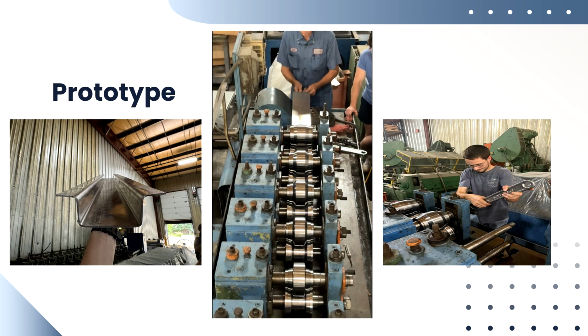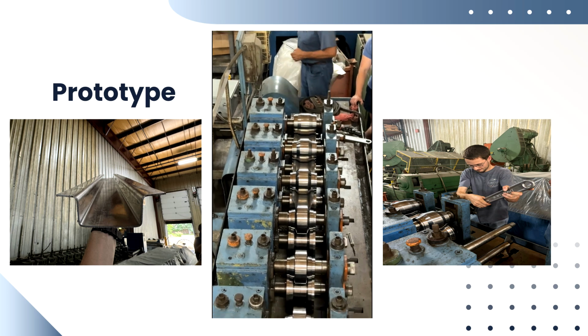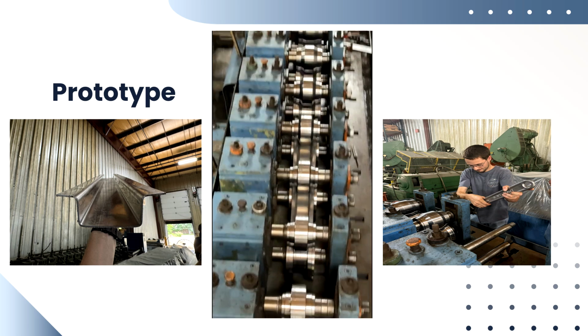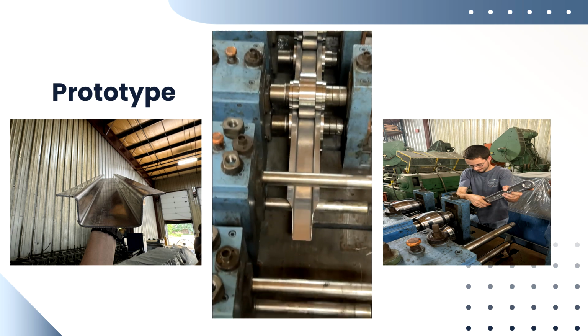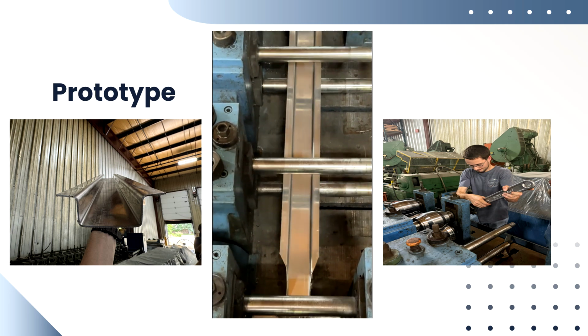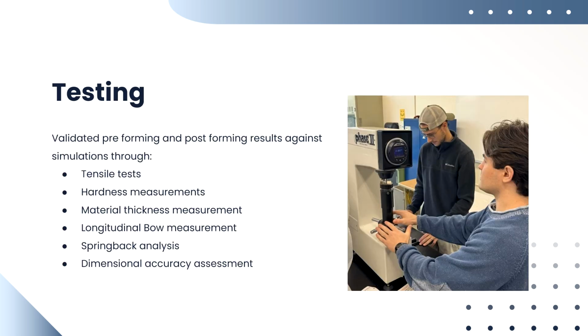With the final roll sets manufactured, the team conducted prototype testing using both 6061 T6 and 7075 T6 aluminum. Prototype parts were formed using the 7-pass setup at Roll Form Solutions. Key characteristics like ultimate tensile strength, hardness, and thickness were measured before and after roll forming to evaluate changes caused by the forming process. After forming, the team also assessed longitudinal bow, springback, cracking, and dimensional accuracy. These results were then compared to the simulation outputs to validate the accuracy of the model.